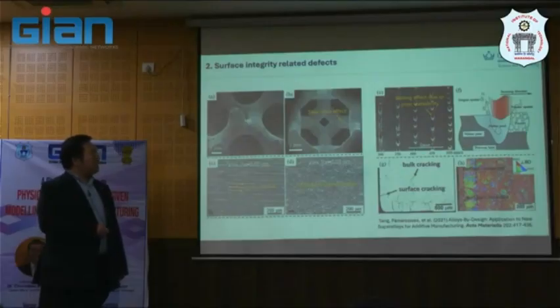at different locations here. So at the edge, it is due to the rapid cooling, which is different from in the bulk. So this sample we do only 10 millimeter thick. It's not very big anyway, but there's still some micro crack and then macro cracking here. And I think this is related to the scanning pattern we use, because at the edge and in the middle we change the way we print it. So that is something to improve.